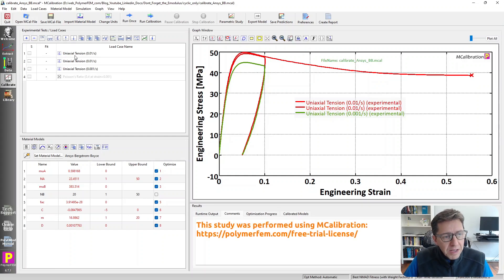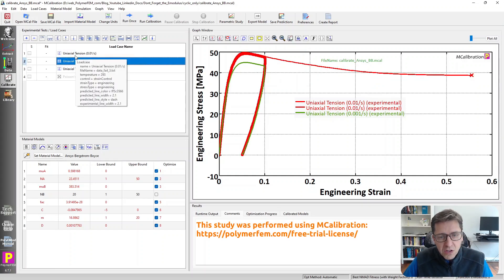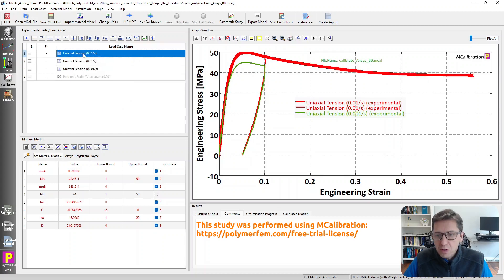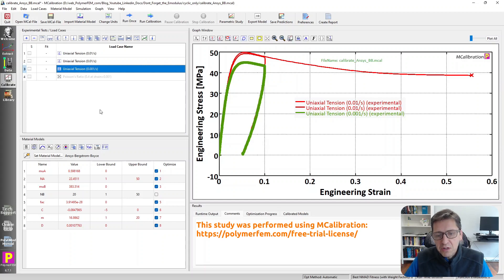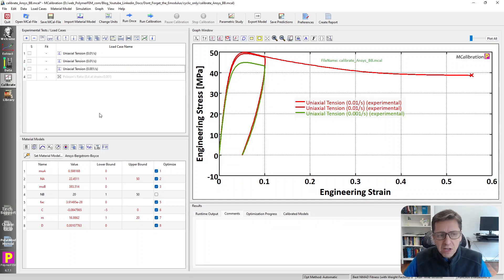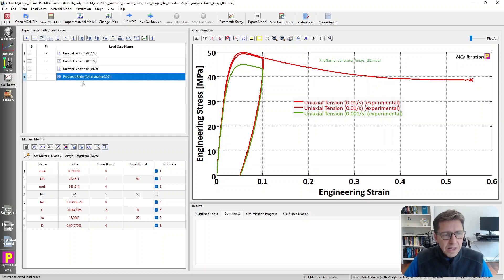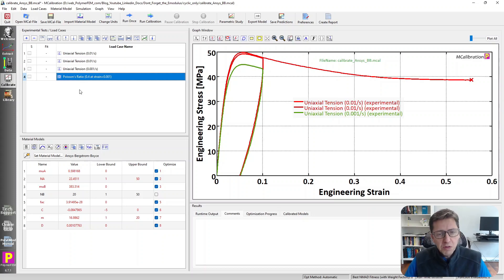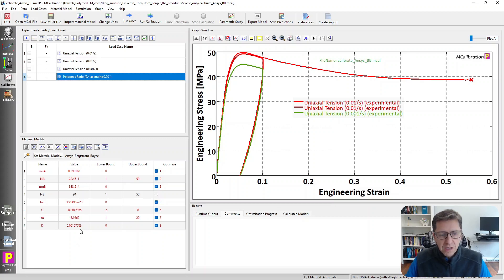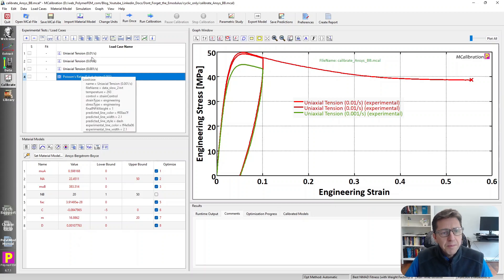I have experimental data. There are two different tension strain rates. One of them is loading and unloading, and one is just monotonic. And then I have a test that was 10 times slower in green here. I already calibrated material model to this data, and when I calibrated it, I added in MCalibration a Poisson's ratio value that I want to target. So I don't have to specify the bulk modulus or in ANSYS the D parameter, which is the one over the bulk modulus or something like that.